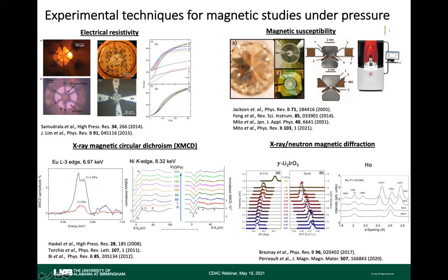And this makes the high pressure experiment, especially electrical resistivity experiment, a lot easier than the traditional way of laying out these electrodes by hand, which requires a special skill with a high precision placement of the micron size electrodes. And this technique has been used up to 100 GPa, beyond 100 GPa.